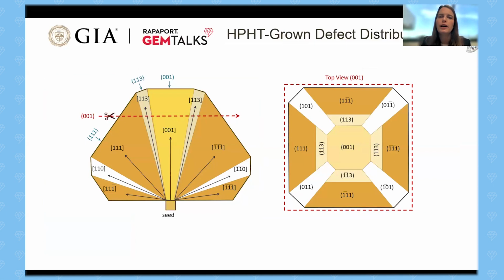If you then move to laboratory-grown diamonds, for instance, those produced by HPHT growth, because of the way that they're growing, the incorporation of defects is going to be influenced. So for instance, in this example here, you have your diamond seed at the bottom, and as this crystal was growing along different directions, different defects preferred going in. So in the 111 octahedral face, nitrogen, which can give you yellow color, loves going in. So that section is going to have more nitrogen in it. And if you were to slice through it, you're going to have what's known as a Maltese or cuboctahedral pattern. So you have a square with a cross shape going through it. Again, very distinctive to what's seen in natural diamonds.